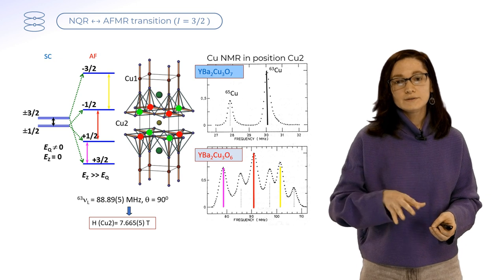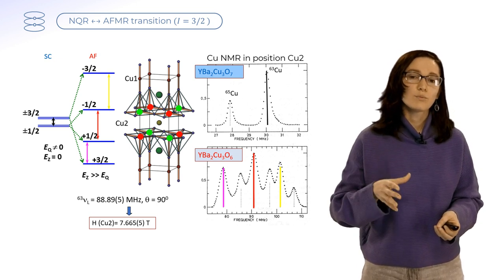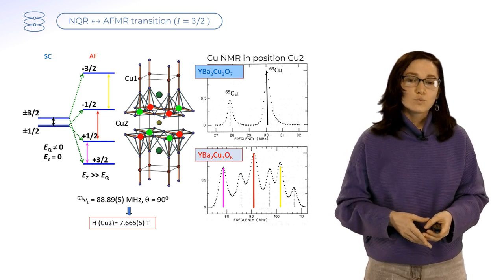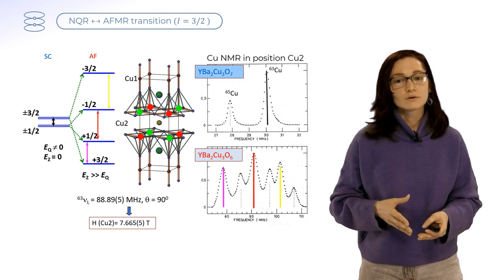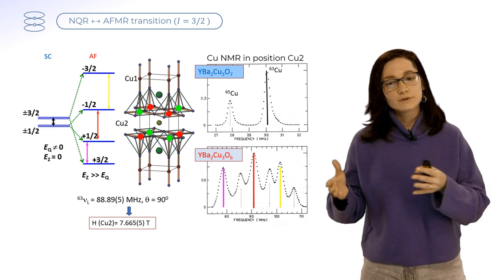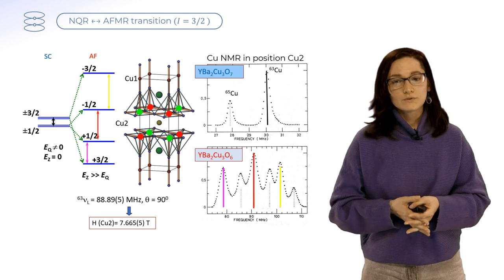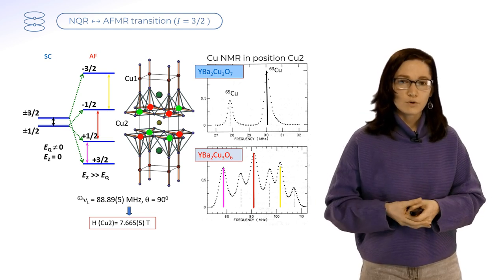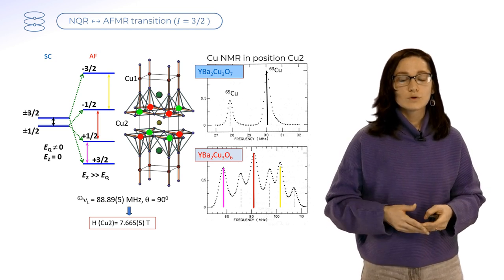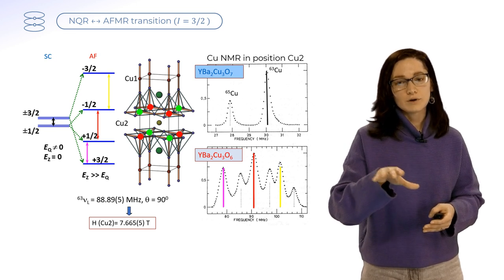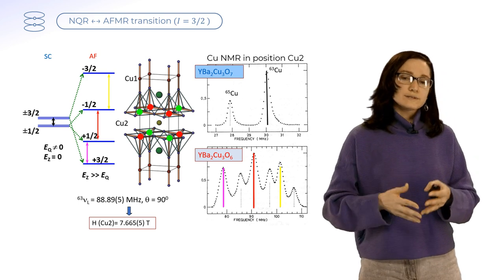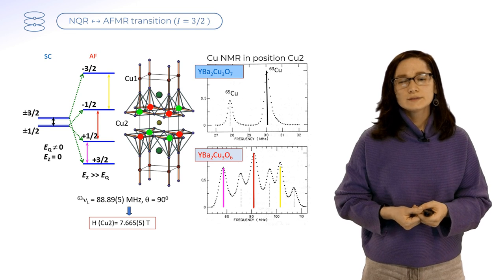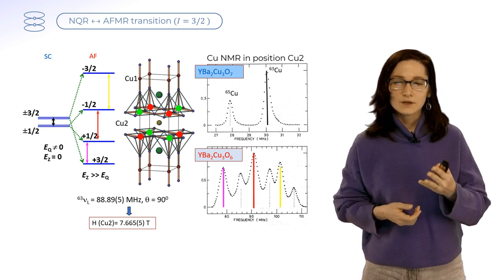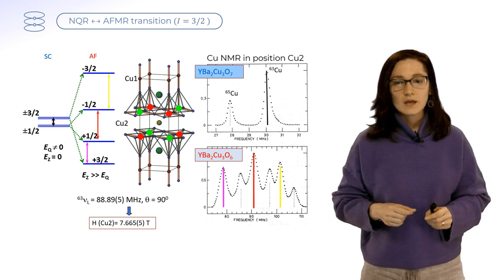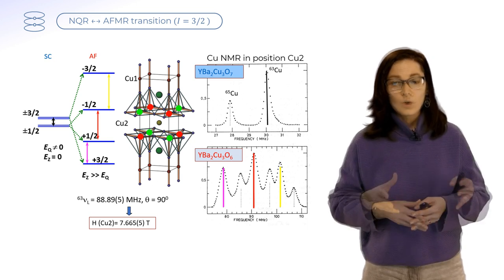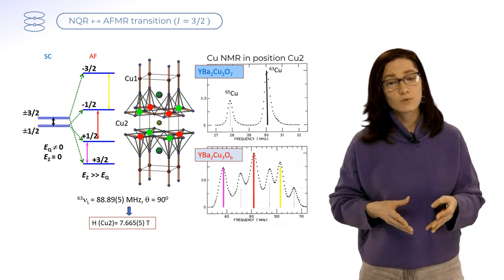We didn't even need the external field for it, because there is a field on the copper atoms without external field. So we measured the NMR spectrum for extreme compounds with 6 oxygens and 7 oxygens. What did we find? Do you remember that there were 2 isotopes of copper in the table above? So here we will look just at one isotope, and the other lines we're not talking about are the lines for the other isotope. Here we can see that the spectrum for the antiferromagnet has 3 transitions and 3 lines, yellow, magenta, and red lines, and they are located at 90 megahertz, a very big field. While in case of the superconductor, we have only one line.